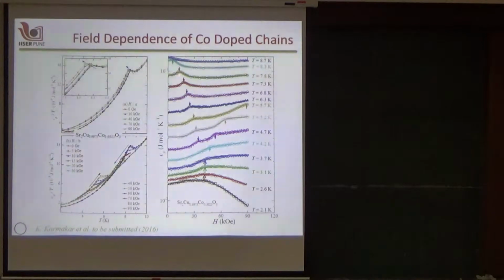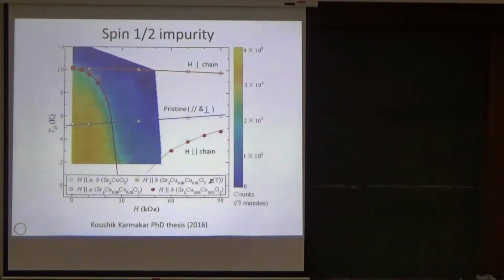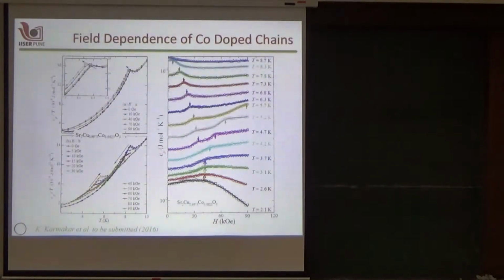This has been seen in isothermal specific heat measurements also. So these are specific heat isotherms, and you see the one transition which is getting suppressed and then a new transition which is appearing. But this happens only along the chain direction when the field is applied parallel to the chain. When the field is applied perpendicular to the chain, it does what a typical antiferromagnet is expected to do, which means the transition temperature decreases slowly, gradually with the increasing magnetic field.